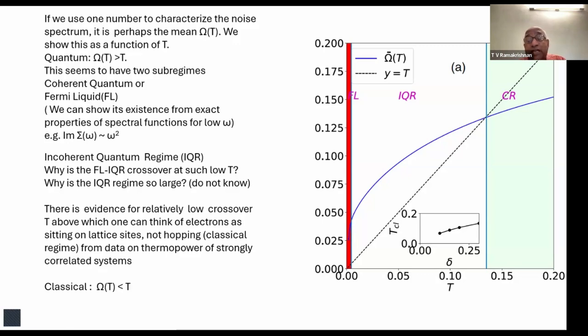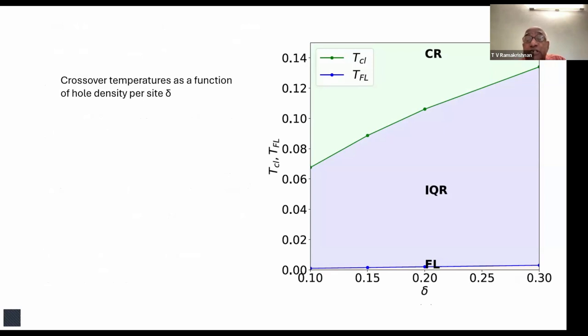So we show that result in the next slide. Here you see the three regimes, one which is confined to extremely low temperatures, where the imaginary part of the self-energy and the real part of the self-energy are those which correspond to a canonical Fermi liquid. That is shown here, the Fermi liquid regime as a function of doping and temperature. You see that it is there at all dopings, but at extremely low temperatures. Below this temperature, it is a Fermi liquid, and above this temperature, it's an incoherent quantum liquid. We call it the incoherent quantum regime.